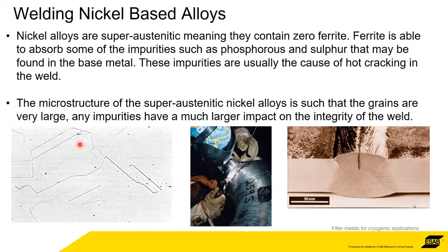When you're welding and diluting, the sulfur goes into the weld metal. You're actually changing the solidification temperature of that part of the weld. Basically, whilst you're welding, the strength of the weld is not sufficient to hold it together, and then you get this phenomenon, hot cracks, right down the center of the weld. So without having sulfur in there, any kind of impurities can cause a lot of problems.